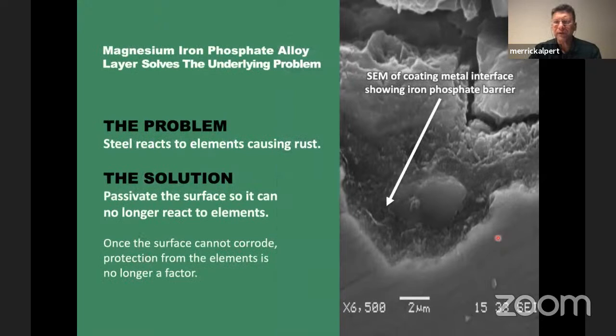Now, what I want to show you here is the same scanning electron microscope photograph, but in this case, we're annotating it to really emphasize the fact that if you look at the root cause of corrosion, it's occurring because you have a reactive surface. It's occurring because oxygen and moisture can touch that steel and steel will corrode. So what we do with Eon Coat is we go right to the root cause of the problem. We passivate the surface of the steel. It can no longer react with the elements. And because oxygen and moisture can't touch the steel, it will not corrode.